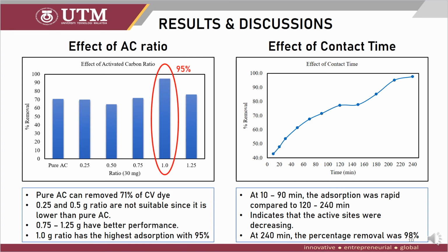So the next parameter is the effect of contact time. As you can see here in this figure, at 10 to 90 minutes, the adsorption was very rapid compared to 120 to 240 minutes. This indicates that the active sites were decreasing over time. At 240 minutes, the percentage removal was about 98%, which is completely removing the crystal violet dye.